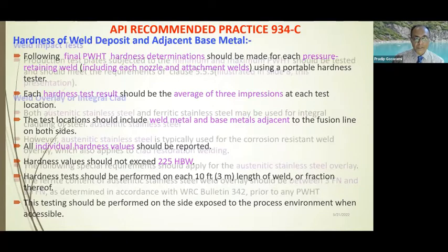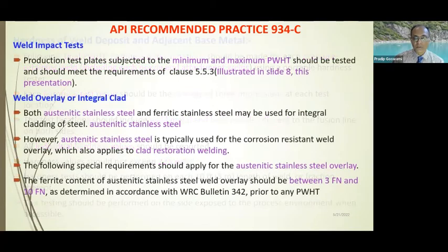And continuing on that note, we need to have the impact test on production test plates, production coupon plates. They should be subjected to a minimum and a maximum post-weld heat treatment. And they should be tested to meet this particular clause. And this particular clause is again on the impact values, that is 40 foot-pounds or 54 joules. And that particular requirement has to be met.